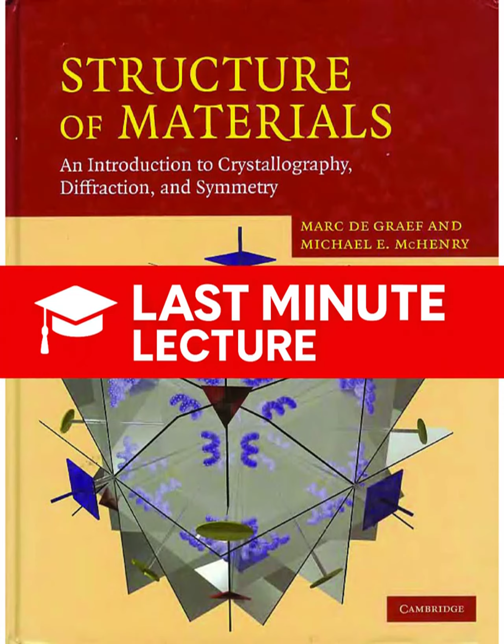Can you give us a quick example? Sure. In a cubic crystal, think about the 100 plane. It has 6 crystallographically equivalent permutations: 100, minus 1, 0, 0, 0, and so on. So for the {100} family of planes, the multiplicity p is 6. Okay. But now consider the 111 plane. It has 8 equivalent permutations: 111, 1 minus 1, 1, and so on, plus their inverses. So for the family, p is 8. So purely because of this geometric multiplicity, the 111 peak will naturally be about 33% stronger than the 100 peak, even if their structure factors were identical.